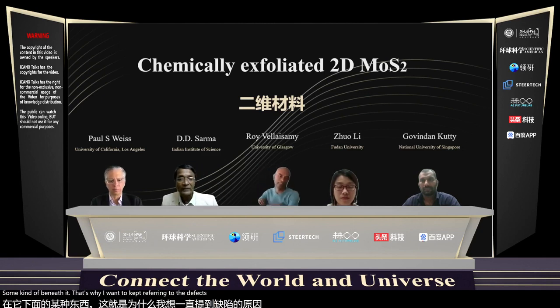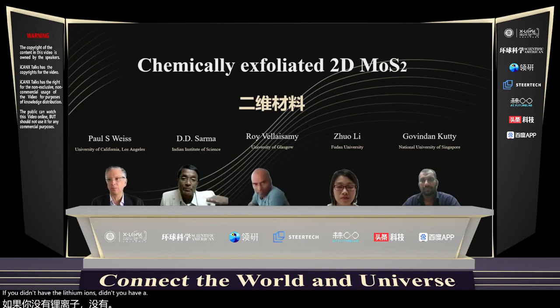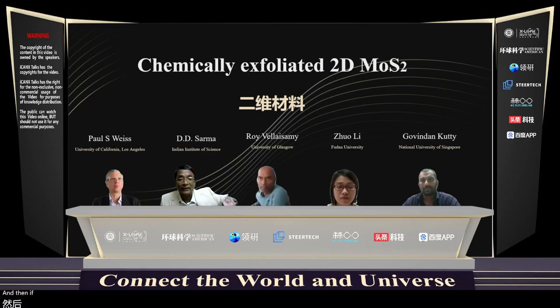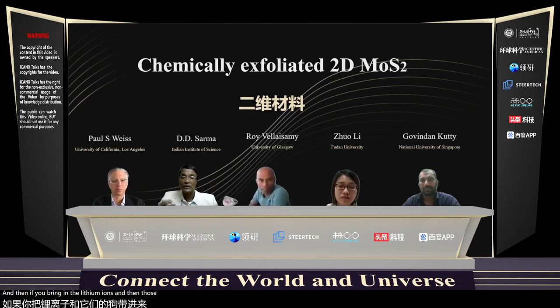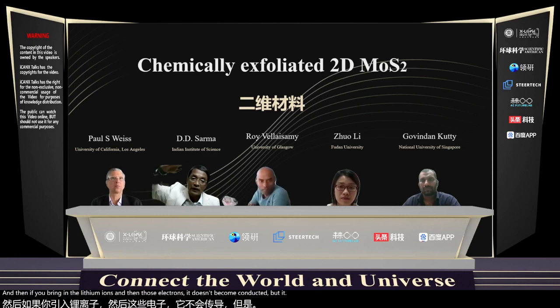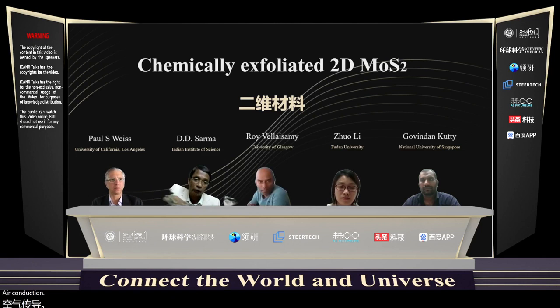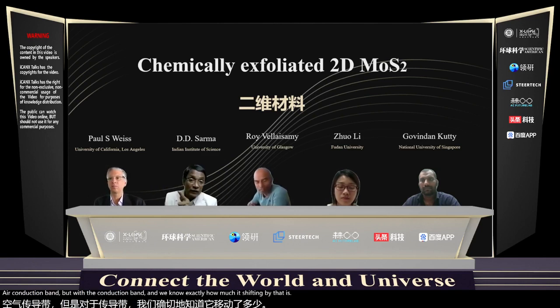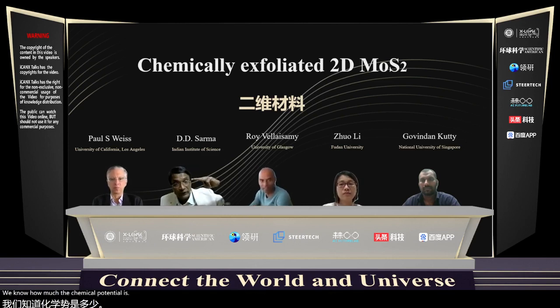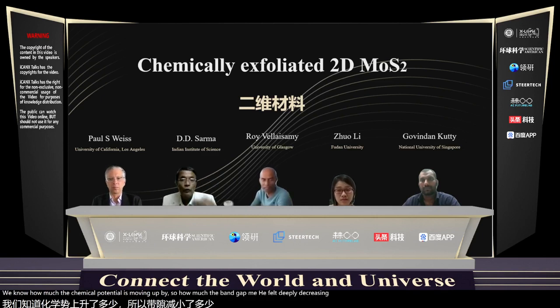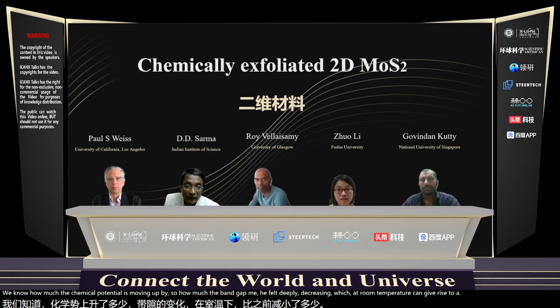If you didn't have the lithium ions, then you have a certain pinning in the defect level. If you bring in the lithium ions and that dopes electrons, it doesn't become conducting, but it moves the chemical potential up, closer to the bottom of the conduction band, and we know exactly how much it's shifting by. That is the shift that we saw in our measurement. We know how much the chemical potential is moving up, so how much the band gap is effectively decreasing, which at room temperature then gives rise to higher conductivity.